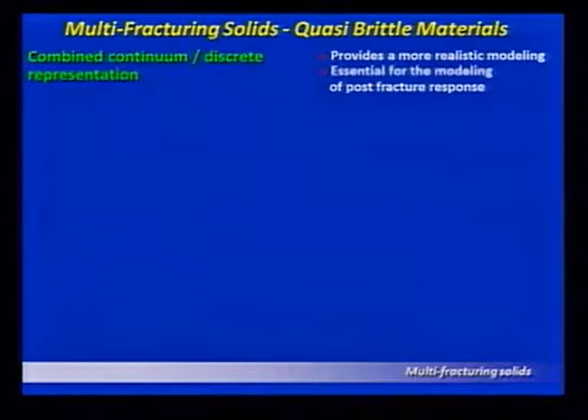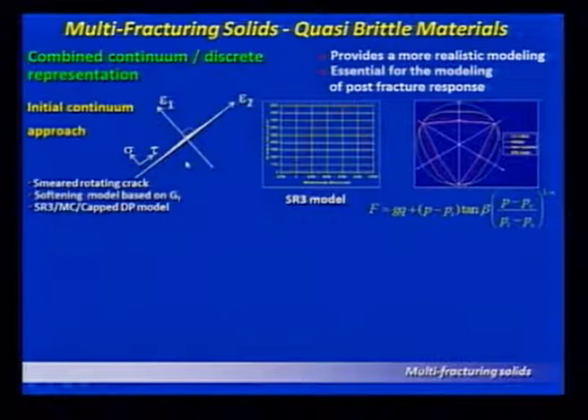Right. So we decide that we're going to model fracture. The approach we've taken is to start from a continuum and then change it into a discontinuum. First of all, we start with a continuum where we model fracture on a rotating crack basis. And then on the compression side, we use some failure surface. It could be anything. We're using what's called an SR3 model, but it could be Mohr-Coulomb, Drucker-Prager, or so on.